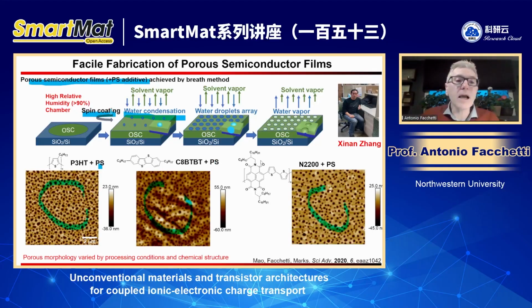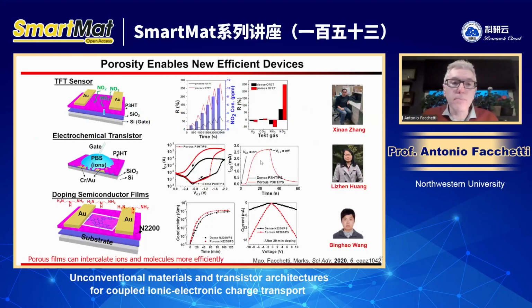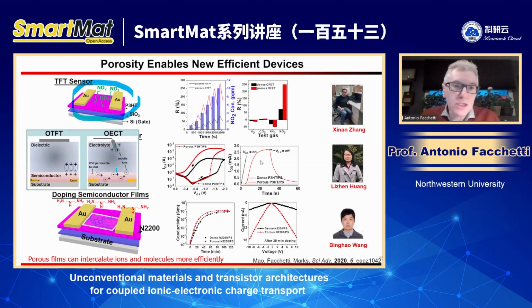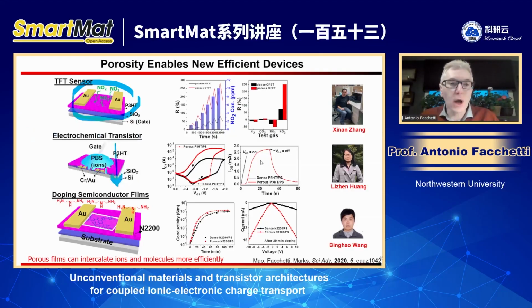We can use this porous semiconductor film to make, for example, TFTs, where because the analyte can penetrate much better, we can have better sensor TFTs. We can make these electrochemical transistors. Recall, in an electrochemical transistor, the ion has to penetrate. And because you have holes, the ion can penetrate, so you can have a higher current compared to the dense film, the film without porosity.